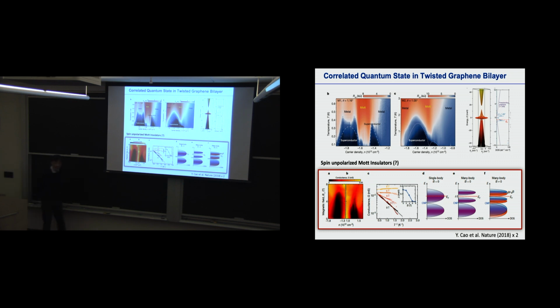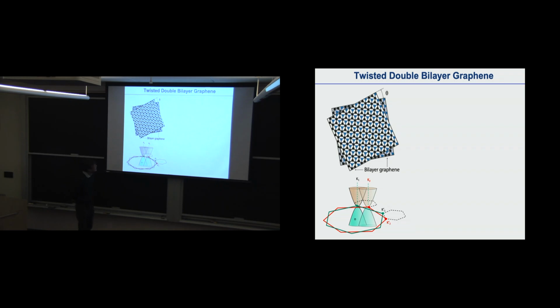So here comes the last pitch of my talk. What we did is repeat a very similar experiment on a different system. The next simplest system is the so-called double bilayer graphene. Each graphene layer is Bernal stacked, and you put these two Bernal stacked layers together with some small twisting angle, giving you four graphene layers total, and we do a very similar experiment.